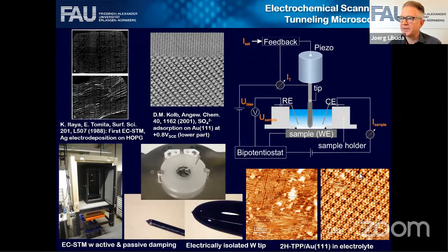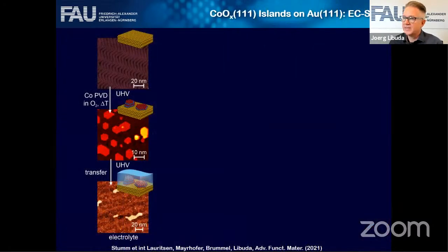But there's one thing that you have to keep in mind with this experiment, and that's that the tip is also an electrode. So there's one very critical difference to the UHV experiment. In the UHV experiment, you would just choose a bias between the sample and the tip. We would choose the bias to tunnel into some states of the material. In an electrochemical experiment, you cannot do that because you're not free with the choice of the bias. You have to make sure that your tip is always held under a potential where it's stable. If you just apply any potential to the tip, very likely you will change the tip. You may dissolve the tip, and so on. So that's a very critical difference to the UHV experiment. You're not free with the choice of the bias. But still the experiment works.